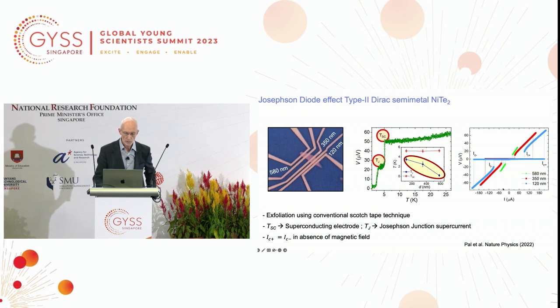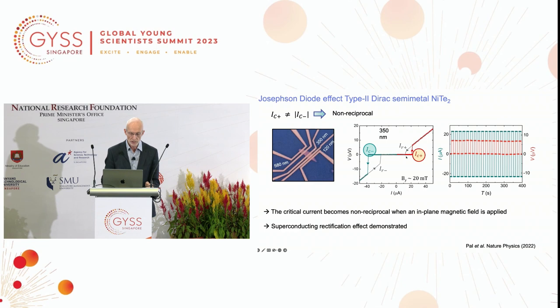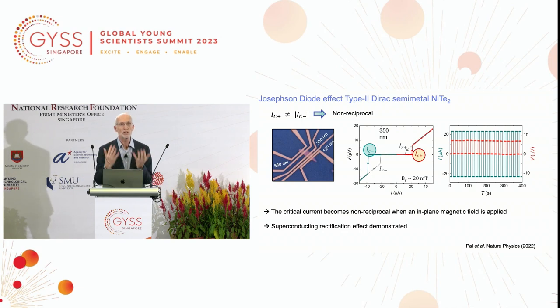And we found at the lowest temperatures that the critical supercurrent density for current flowing left to right or right to left was the same. But in the presence of a tiny magnetic field perpendicular to the supercurrent, we found that these critical supercurrent densities are distinctly different. First time, Josephson diode effect. And this means that if you pass a current to the left, it's dissipation-free. You pass it to the right, it will be dissipative. So we could use this to detect domain walls.